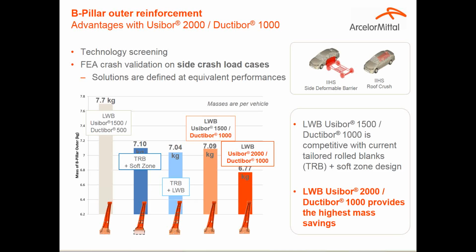And focusing on the B pillar specifically, you see in the graph the comparison of the main solutions today on the market. From the left hand to the right hand side, you see a simple laser welded blank in Usibor 1500, Ductibor 500, or more complex solutions with TRB, the tailor rolled blank, then several thickness variations, and soft zone, or the combination of tailor rolled blank and laser welded blank on the bottom in order to have a ductile material to absorb energy on the bottom of the B pillar.